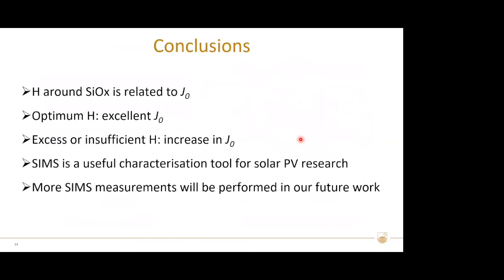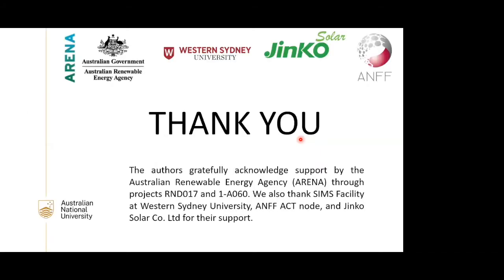In conclusion, we observed that hydrogen concentration around the oxide corresponds to the J0 value in samples after firing. Upon firing, the dielectric coating films release hydrogen into the polysilicon/silicon-oxide stack. Our results suggest that an optimum hydrogen level surrounding the oxide provides excellent surface passivation after firing, while excess or insufficient hydrogen can both lead to surface degradation. SIMS is a very useful characterization tool for solar PV research, and more SIMS measurements are required for our future work.